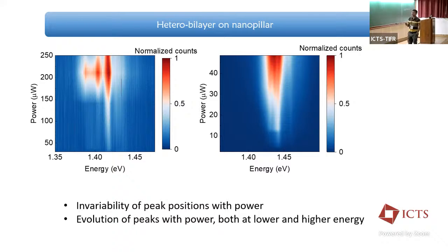But before that, if I just look at a single peak, there's really not much of a movement. If I compare this with the flat Moire sample, if you increase your power, because of this dipolar repulsion, by the way, the dipolar repulsion is very, very strong in these Moire samples, the heterobilayers, because the electrons are in one layer and the holes are in another layer. So this electron-hole attraction is diagonal, but electron-electron and hole-hole are in the same layer. So the entire dipole will start repelling.